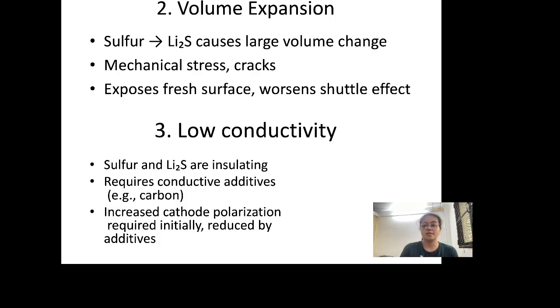So these are the compounds that form the bulk of the cathode, which means even if the electrochemistry of all the other compounds is fine, there is a limiting factor in the electron transfer inside the cathode, and that is the fact that the cathode materials are lower conductivity materials. To work around that, the electrochemical brute force way would be just higher polarization, and you work around the fact that they have lower conductivity.